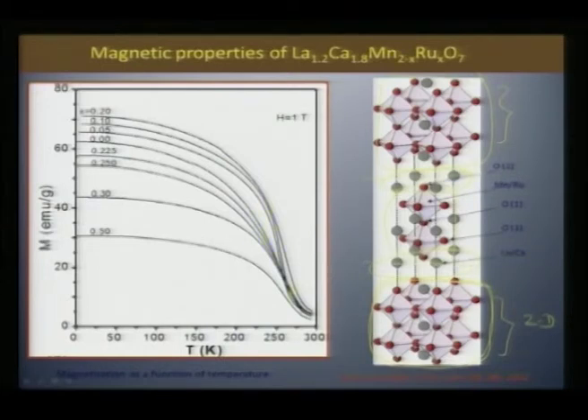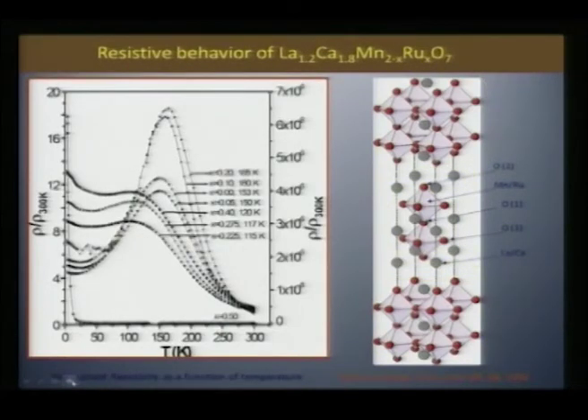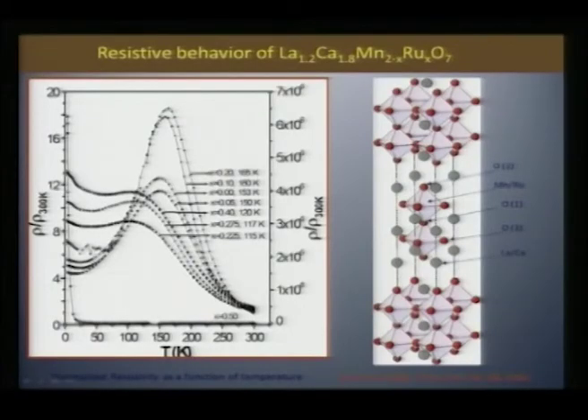In such a case you would see for a parent compound the ferromagnetic transition is somewhere here, whereas if you start substituting ruthenium here in the manganite, you would see that there is an increase in the ferromagnetic transition up to 20%, and then the ferromagnetic transition drops down. Okay. Now, if you look at the metal to insulator transition, that is again interesting.